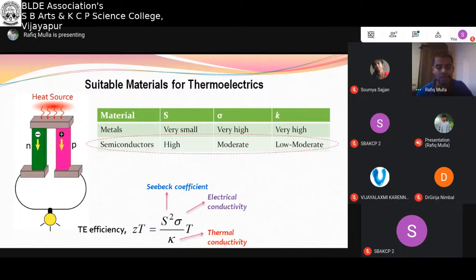Another question is from Anirudh Kulkarni. When working on an automobile exhaust waste heat recovery system, the cold side temperature of the thermoelectric generator is 60 to 70 degrees, and I am unable to maintain the cold side temperature by using a water jacket, heat pipe, or any other method. Yeah, this is actually a practical problem associated with thermoelectric technology. People are working on finding better heat sinks. That itself is a research area now, because in these devices we must have some heat sinks. When we heat this side, heat is ultimately flowing slowly from this side to this side. Even though they are semiconductors, they still allow heat from the hot side to the cold side. Initially you will have a sufficient temperature gradient, but after some time the temperature of the cold side increases, and that is a very big limitation of this technology.